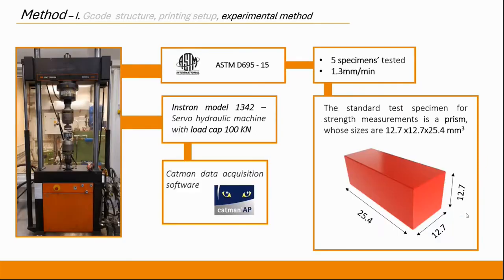The wrinkles on the soft membrane will be triggered by a compressive force acting on the substrate. Therefore, a compressive mechanical property evaluation for rigid plastic was carried out following the ASTM guidelines. To prepare the specimen so that the mechanical properties can be used to describe the behavior of the bilayer specimen, we reproduce the same printing pattern and loading condition as in the leather-like membrane. The specimens used to evaluate compressive mechanical properties are printed with a ±45-degree pattern. The test specimens were designed in compliance with the ASTM regulation, which provides standards for specimen dimension for strength measurement.